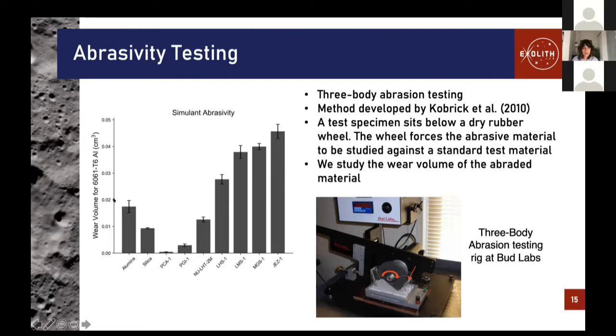So the graph that I've shown here, the vertical axis is the wear volume of a standard aluminum. We chose aluminum because that's what many spacecraft are made of, so it's the most relevant. And then we look at what volume in cubic centimeters of the aluminum was worn away by different materials. So on the left here, these are kind of our standards: alumina powder and silica sand, essentially. And then we've looked at a number of simulants.